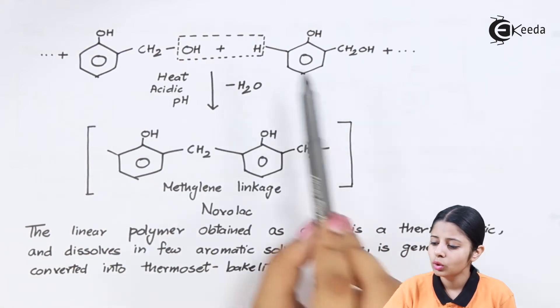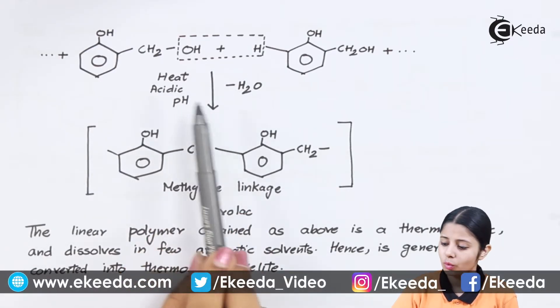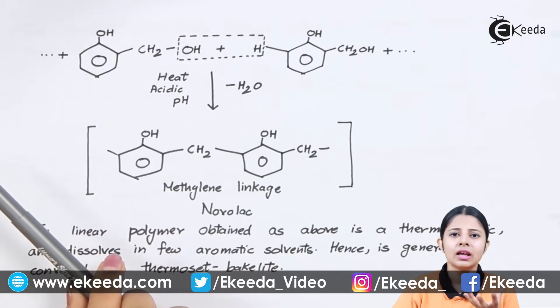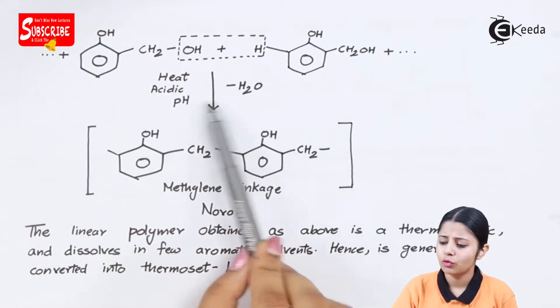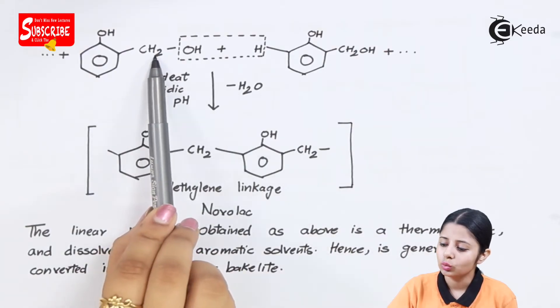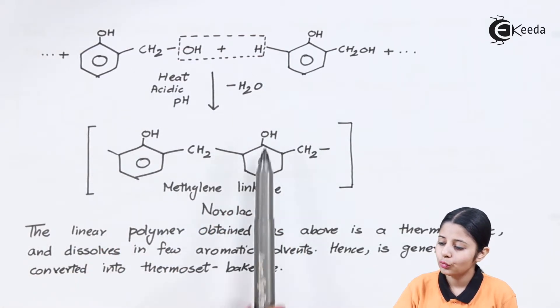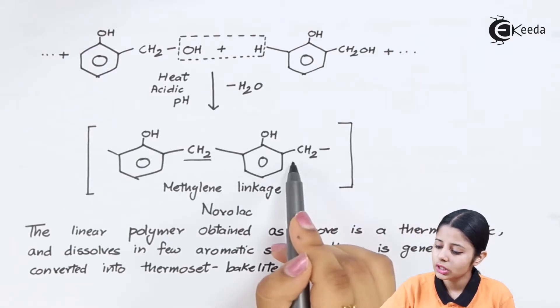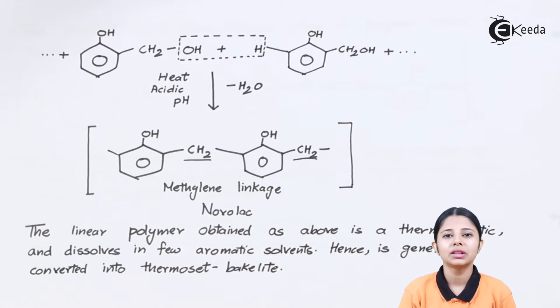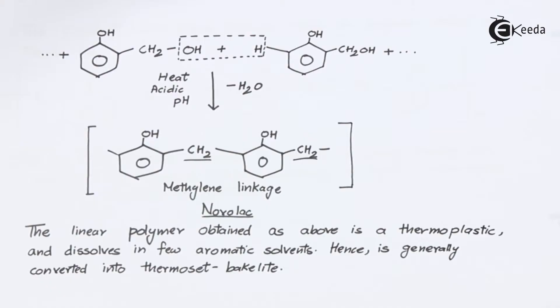Step two: monomethylol phenol — ortho or para — can undergo polymerization to give low molecular weight polymers known as Novolac. Taking O-methylol phenol, the CH2OH group of one monomer and the H from an adjacent OH on another monomer are placed in a dotted box — they combine to form H2O which is removed as byproduct. What remains is a CH2 group linking the two phenol rings together. This CH2 linkage is called a methylene linkage, and this methylene-linked structure is Novolac. Our second step was the formation of Novolac.